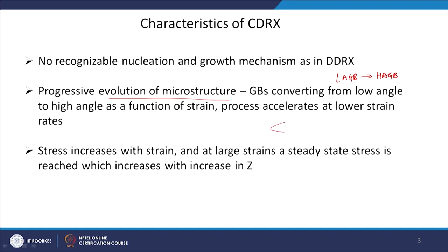In dynamic recovery, you have big grains with small sub-grains inside them — the big grain boundaries being high angle grain boundaries, and the internal sub-grain boundaries being low angle. Now these sub-grain boundaries — all low angle grain boundaries — will in the process convert into high angle grain boundaries through large amounts of continuous strain.